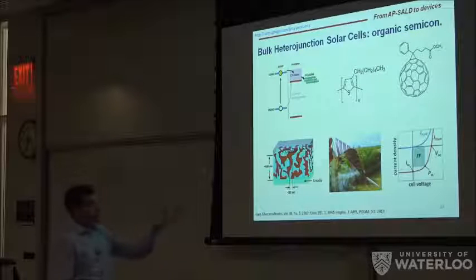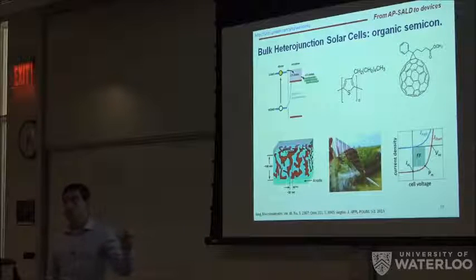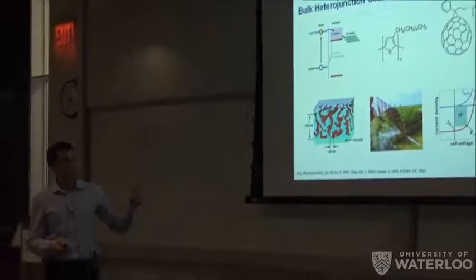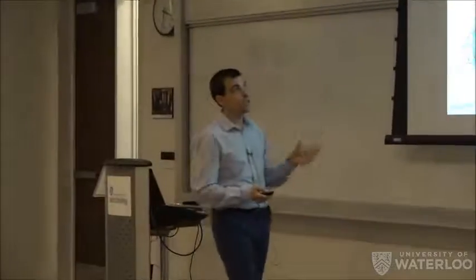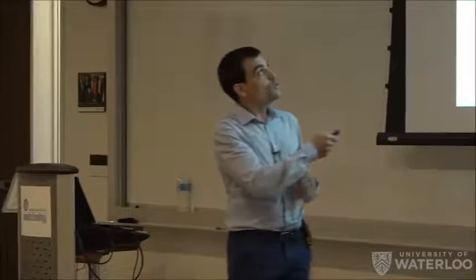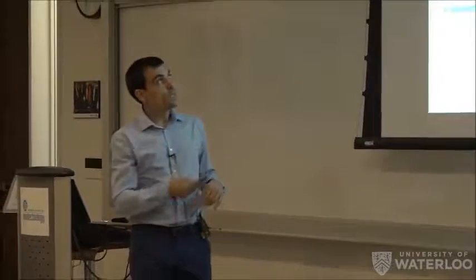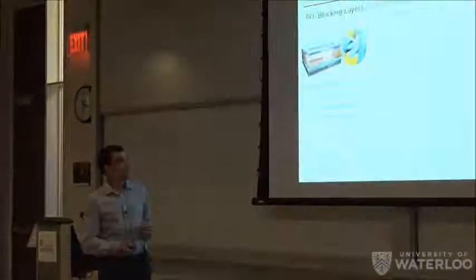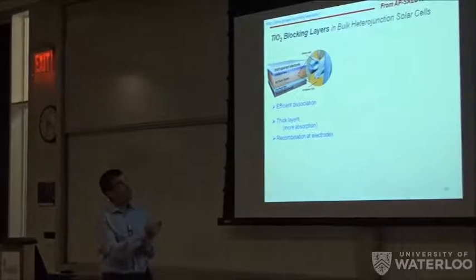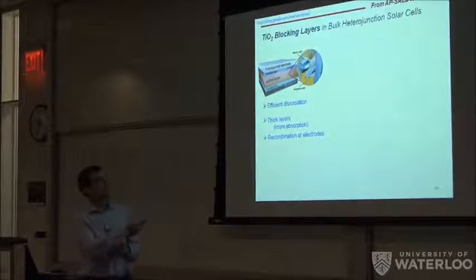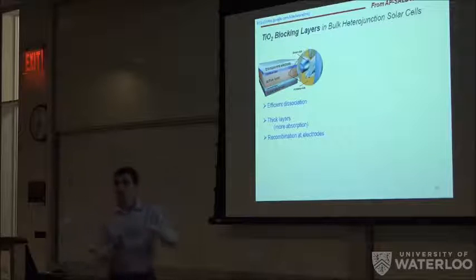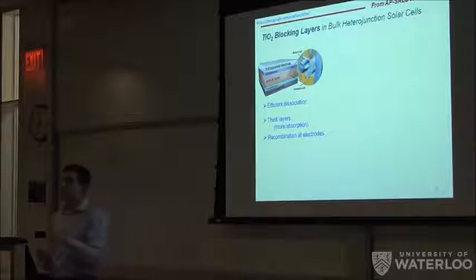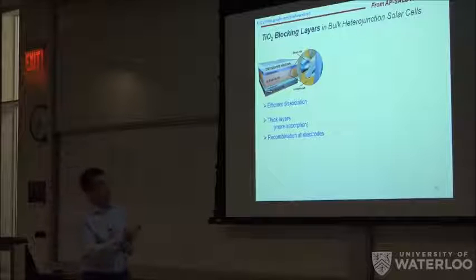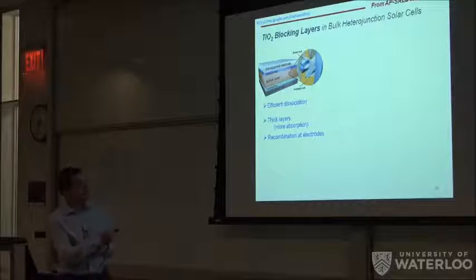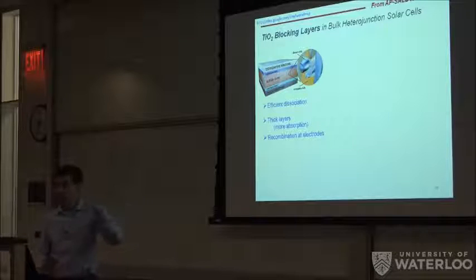So again, we wanted to apply spatial atomic layer deposition to this system because, as I say, it's a system that is processed in liquid, roll-to-roll, fast, high throughput processing, at low temperature. So if you want to make some of the components in a compatible way, you need to have a good processing method. In this case, what we wanted to do is this interfacial layer. As I said, you have a bulk heterojunction layer here in which charges can reach both electrodes. So in order to prevent recombination in the electrode, you need to make these electrodes more selective so that only electrons or holes will be allowed to reach the contacts.